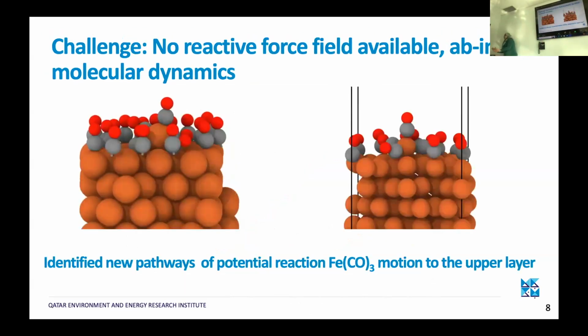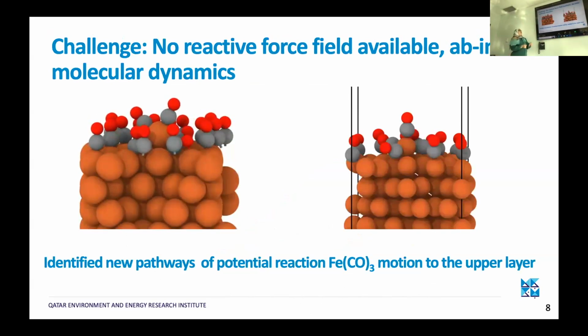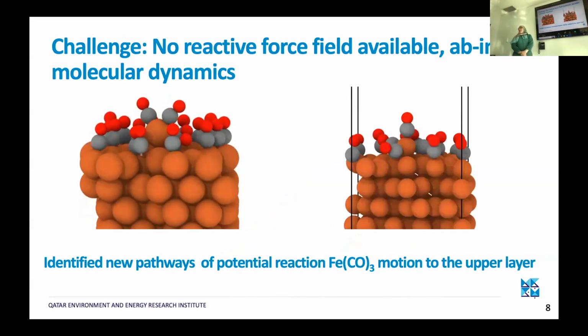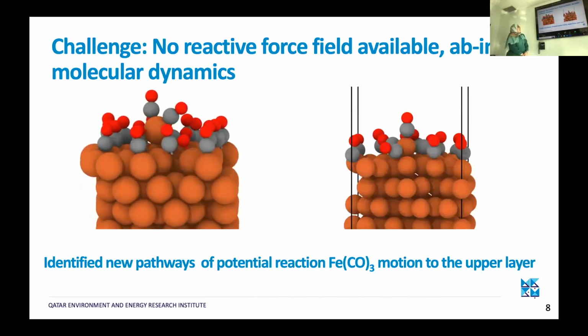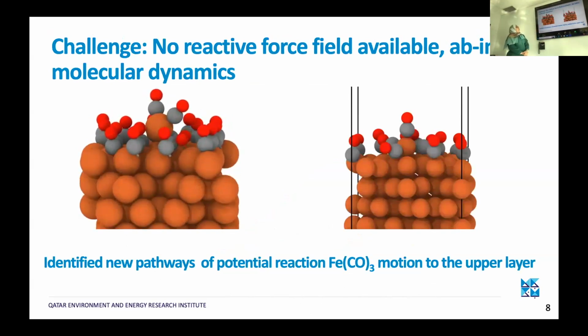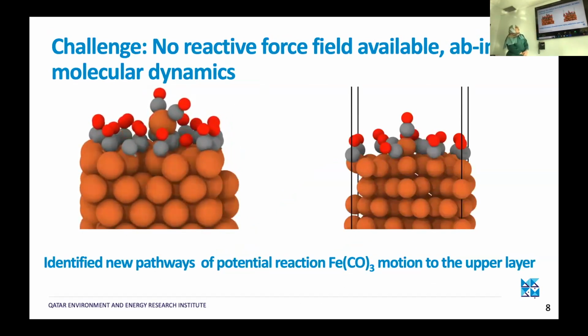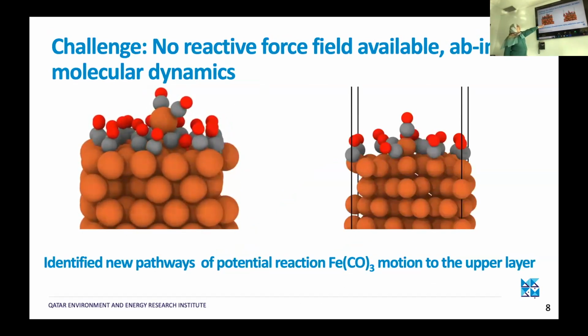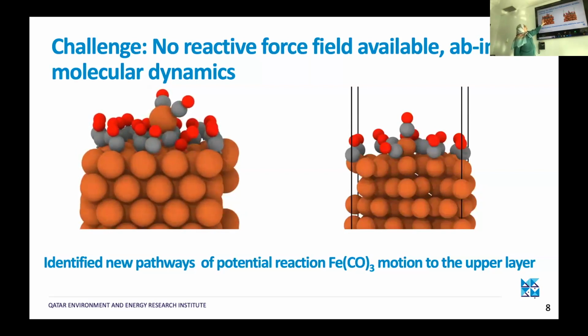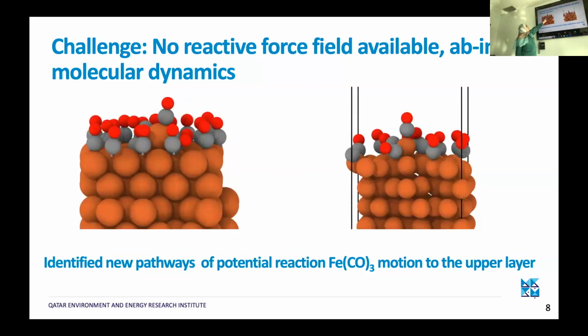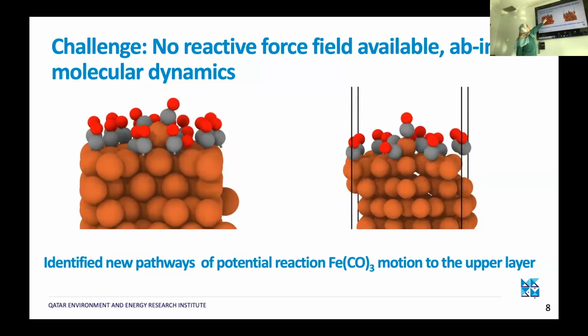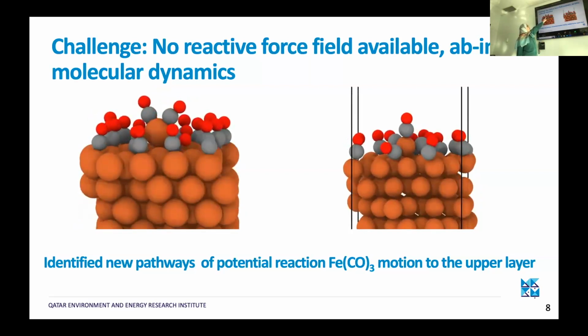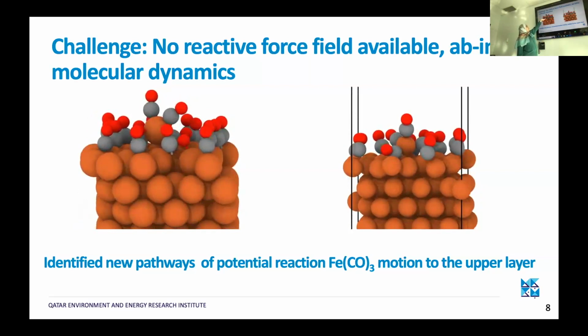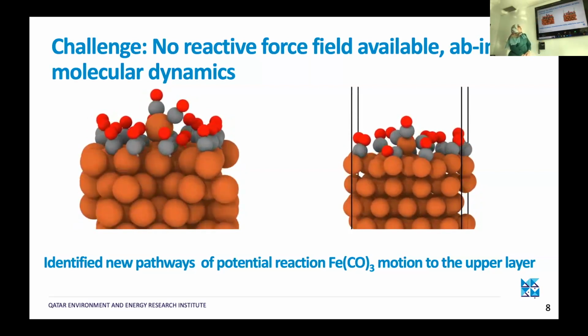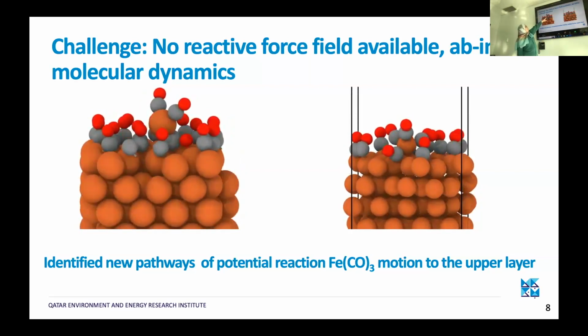Luckily, we have enough computer power. So what we did is that we did DFT calculations, ab initio MD, and we let the system evolve. And then we noticed this movement here. You see that there was an iron atom that has been removed from the surface, due to the reaction with the CO molecules, and it has hopped on top of the CO molecules. You can see that, yeah.